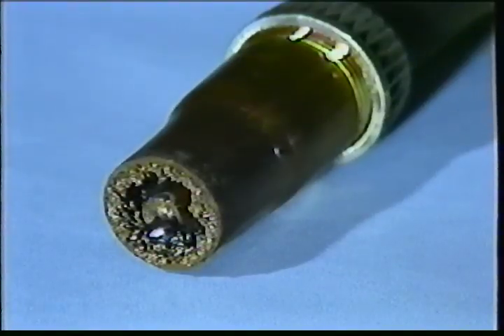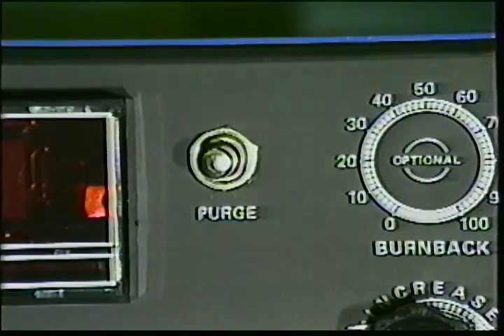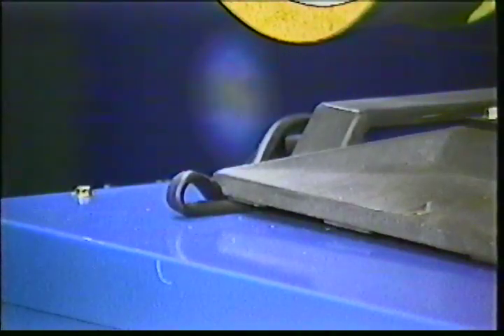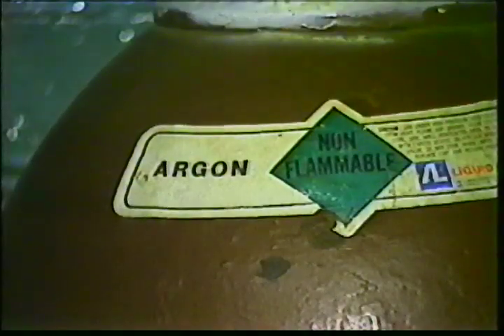Spatter accumulation in the nozzle can cause turbulent shielding gas flow patterns or a lack of gas coverage, which results in porosity. If no gas flows when the purge button is depressed, the problem could be a defective gas solenoid or something as simple as a pinched gas hose, which could cause porosity. Improper shielding gases or a high moisture content could also cause porosity.